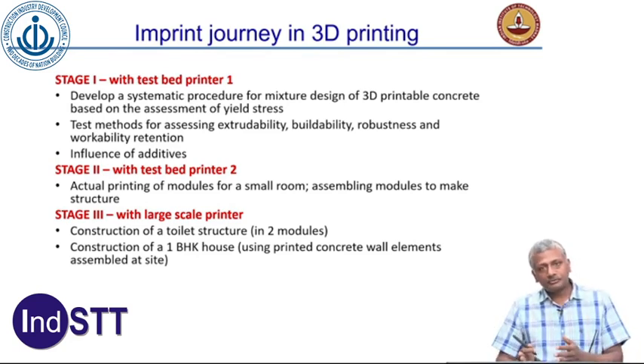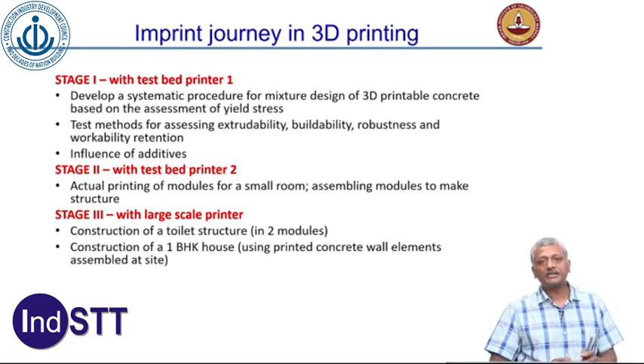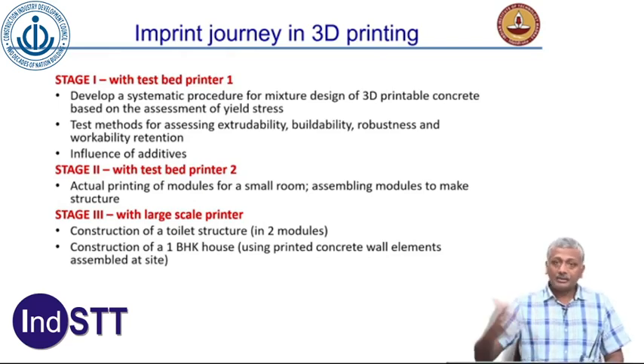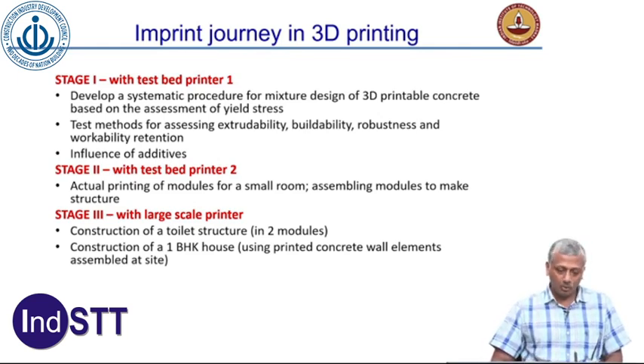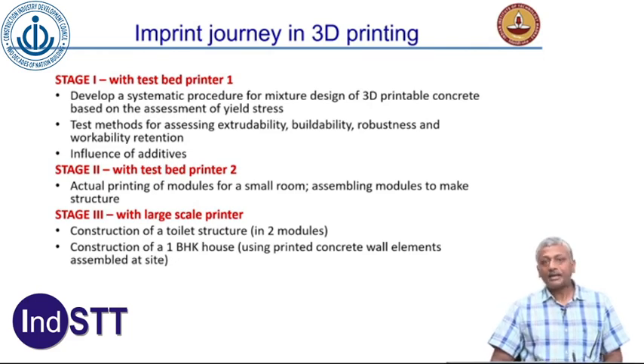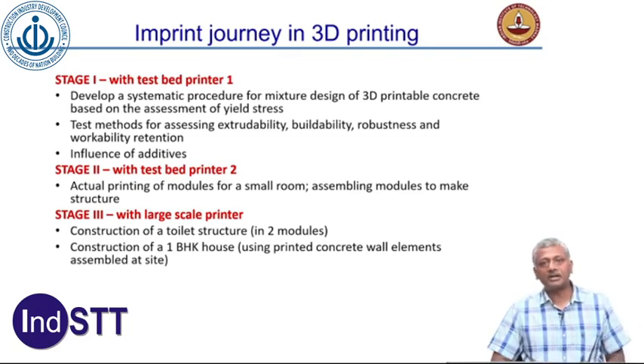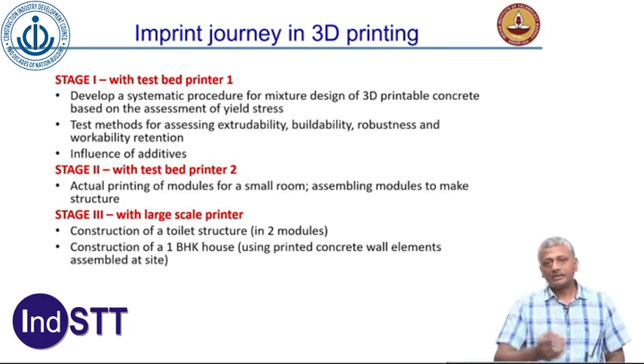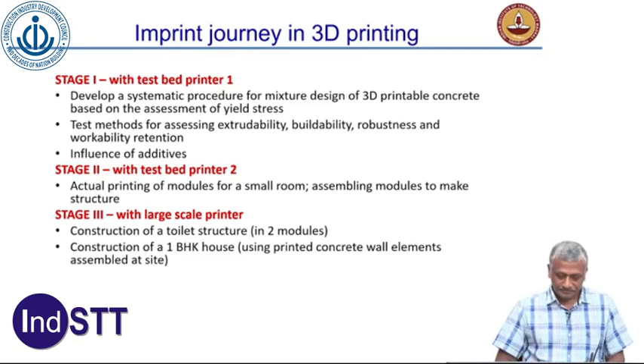Then we moved on to a slightly larger printer, but still it was an experimental printer, research printer, and there we actually printed modules which were assembled to make a small room type structure. Third, we moved on to a much larger printer which was able to print up to about 1.5 meters in one go, and with this we printed a toilet structure in 2 modules. And this same printer is now being used to create wall elements which are 3D printed and are being assembled to produce the first 3D printed house that we may have in our country, that is going to be unveiled very soon. It's not yet ready.